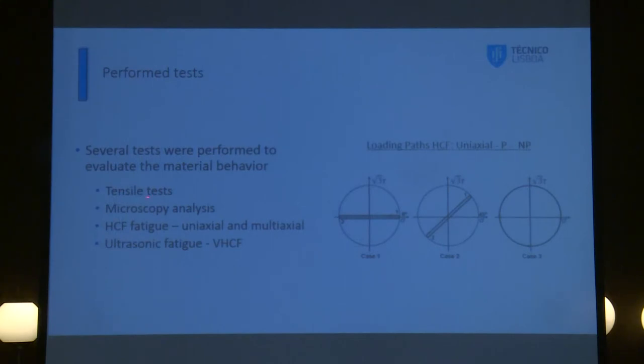Regarding the tests performed, we have performed tensile tests, also performed microscopy analysis, high-cycle fatigue tests, uniaxial and multi-axial. And also, we have performed various ultrasonic fatigue tests. Regarding the multi-axial fatigue tests and high-cycle fatigue, these ones I'm going to present today. Case one is the reference case. We have all the uniaxial conditions, as you can see here. And here, we have the proportional loading. We have the torsion and axial loading. And the non-proportional loading is the circle that appears here, case three. We have managed these three cases.